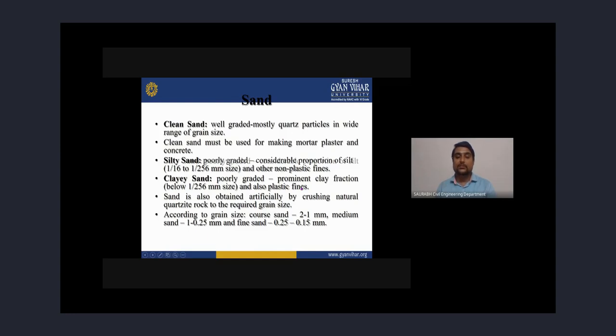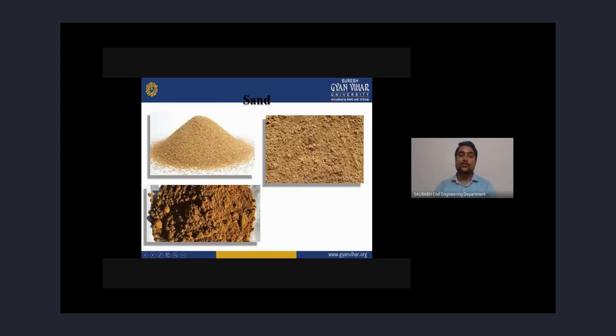According to grain size, there is coarse sand, which has size between 2 to 1 mm, medium sand, which has size 1 to 0.25 mm, and fine sand, which has size of 0.25 to 0.15 mm. Now you can see the images of different kinds of sand.